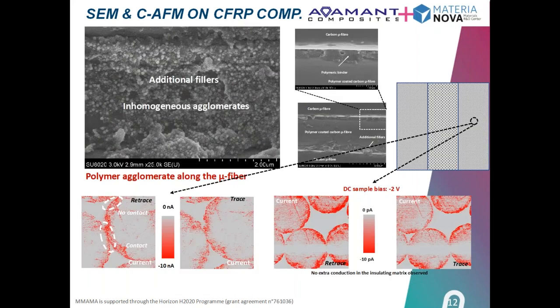Finally, with our composite samples, we did some nice work also with Materia Nova. We did some SEM where we took the physical morphology. We found the additional fillers that we put, and then did some conductive atomic force microscopy. We were trying to see how the current is being conducted through our samples. So the idea is to check, of course, we see here that the fibers are the most conductive part, but also we're trying to see what happens between the fibers and also in the interface of the layers.